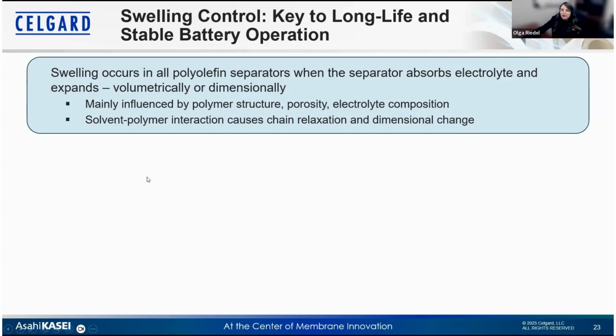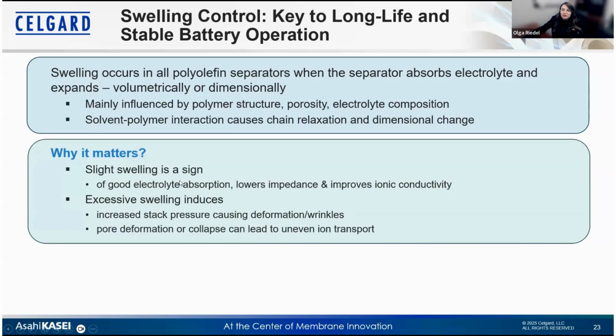So you may wonder, why does that matter? Usually, a slight swelling is actually a good sign since it indicates that the electrolyte is absorbed by the separator and hence lowers impedance and improves ionic conductivity. However, on the other hand, excessive swelling increases the stack pressure and also causes deformation and wrinkles. This can lead to pore deformation and even pore collapse and uneven ion transport, resulting in lithium plating and rapid capacity fading.